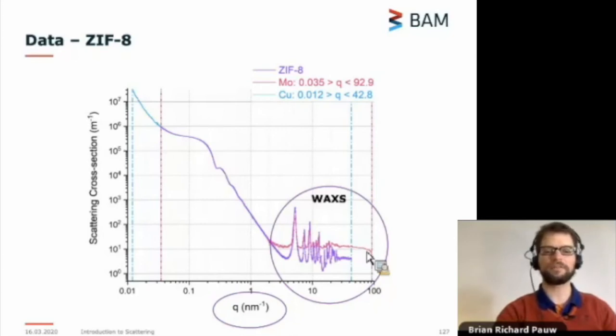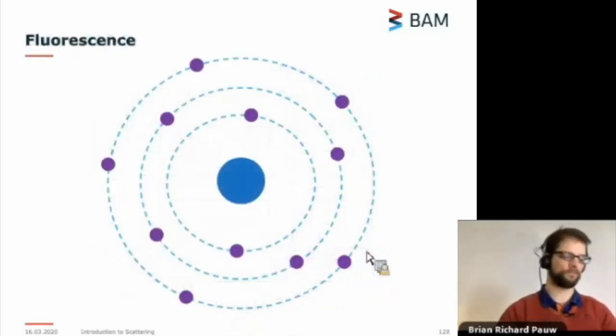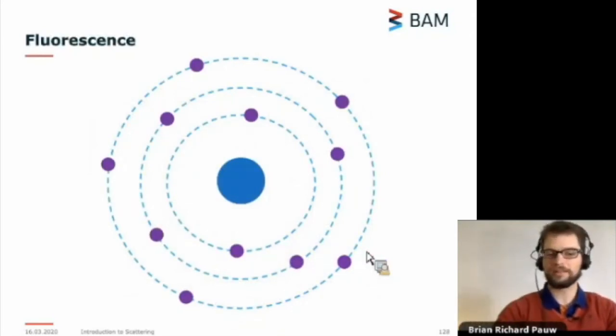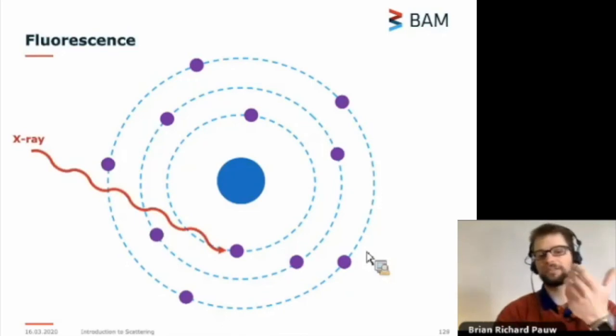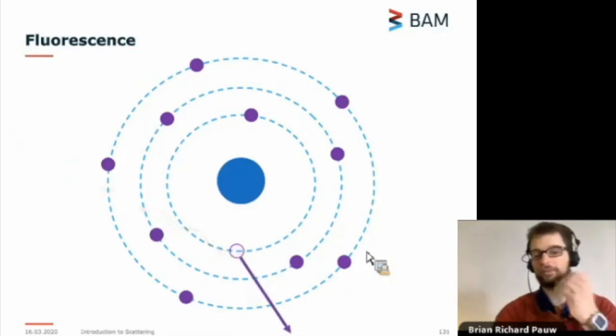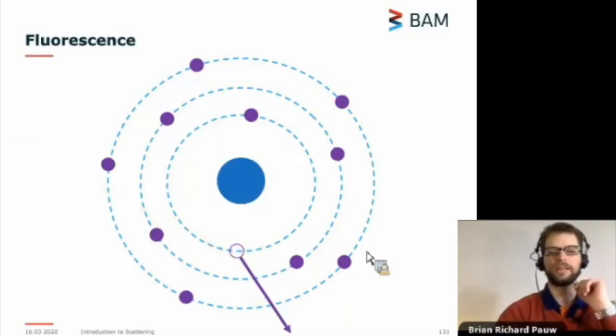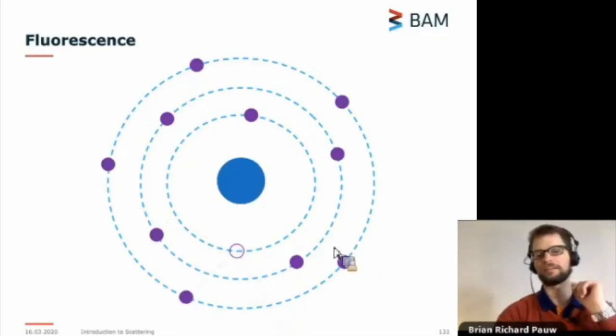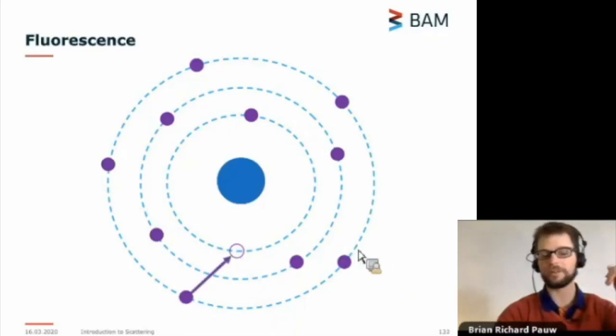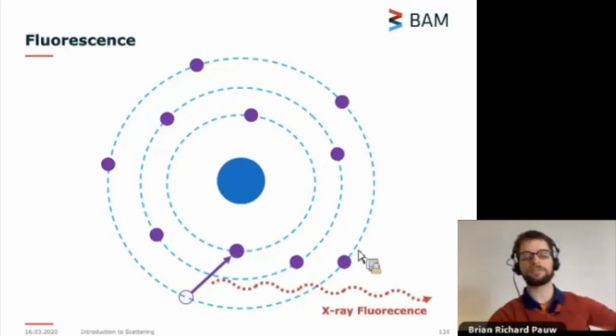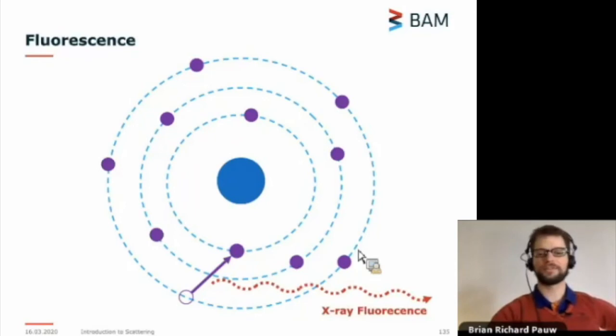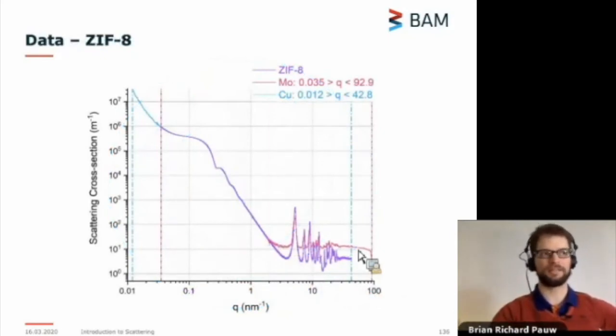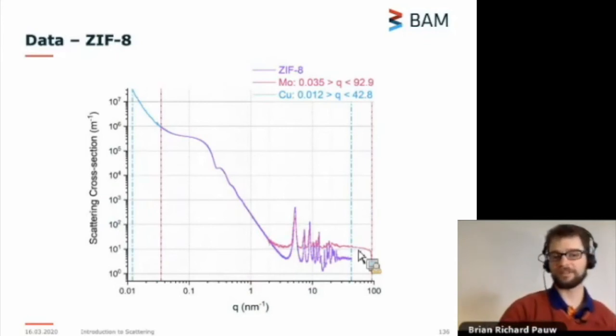Fluorescence is what happens if you have your atom with your electronic levels. You shine at it with X-rays of a particular wavelength, you might kick out one of these core electrons. What happens then is that there's a gap, a space for an electron, and pretty much immediately you will get electrons falling back from higher orbitals into that core orbital. And when they do this, they lose energy, and this gets emitted by means of an X-ray photon, which causes X-ray fluorescence, which we can measure. So this fluorescent signal is really something that comes from your sample. It tells you something about your sample as well. It at least tells you that you might be looking at the right sample if it contains these elements that would fluoresce.